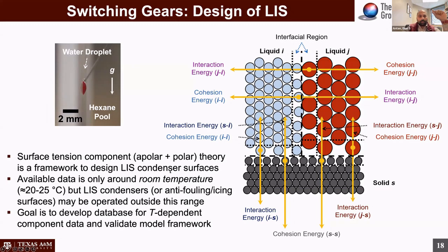But a lot of the design happens with data that's only available at either 20 or 25 degrees C. It's not really consistent either. But as you can see from condensation experiments, they operate anywhere between 65 degrees C for air-cooled condensers right down to close to 0 degrees C for anti-icing applications. And the question is, how do you predict behavior for this wide range of temperature, given that surface tension and interfacial tension change a good amount over that temperature range?